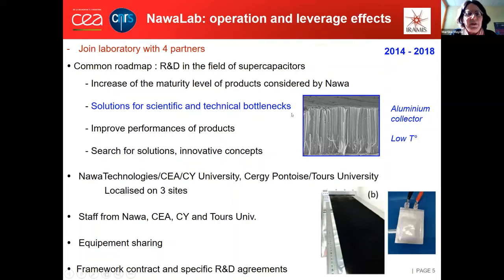So basically, we went to the growth of carbon nanotubes on the collector, on an interesting collector for supercapacitors, which is aluminum. And we had to reach a high efficiency in the growth of low temperature synthesis, since aluminum doesn't afford high temperature such as 800 degrees. So we needed to decrease to 615 degrees the growth of carbon nanotubes to be compatible with the use of aluminum, which was a quite hard job. But we succeeded, and then we improved.